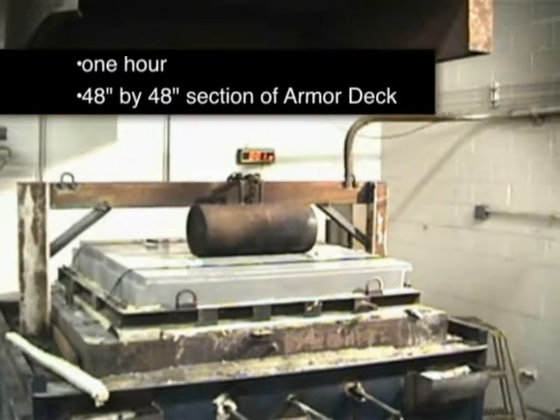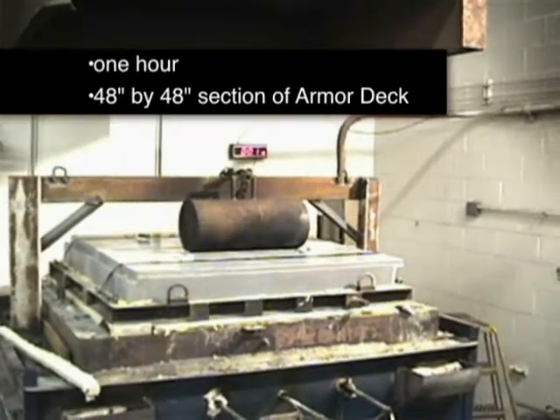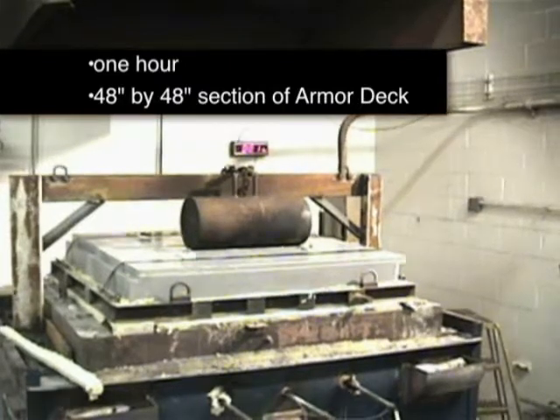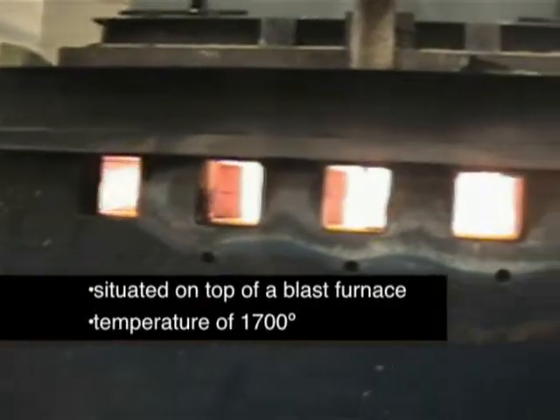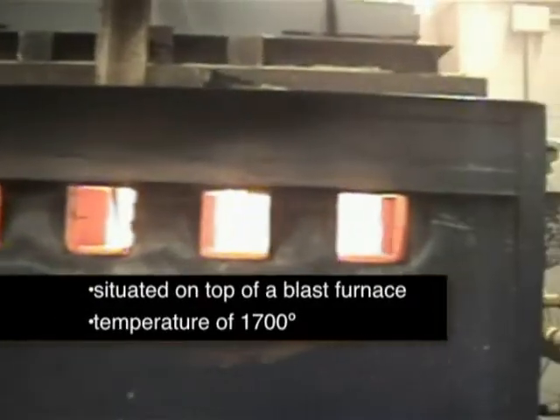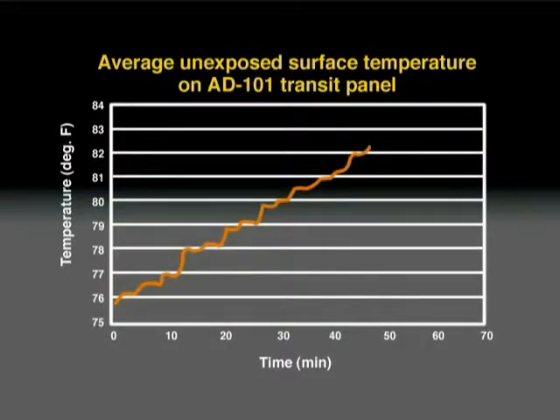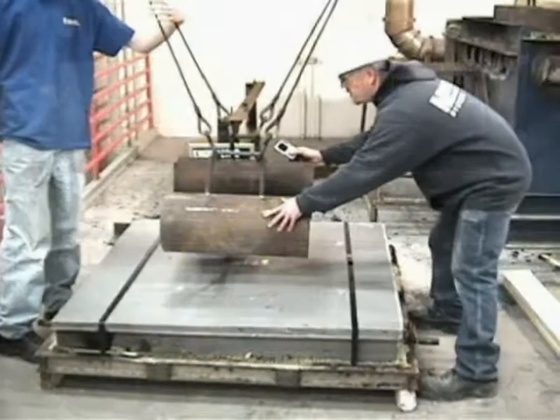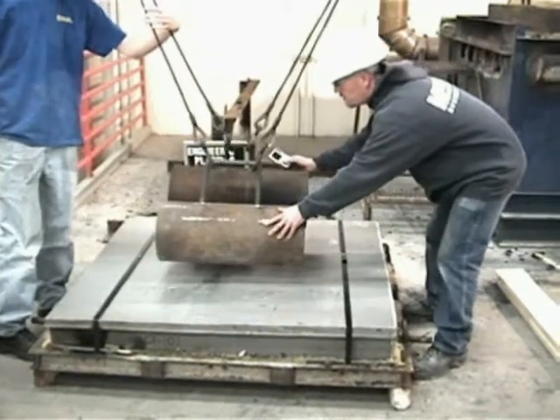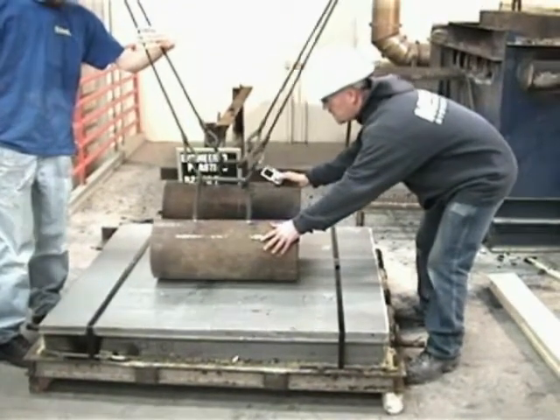The test ran for 1 hour and consisted of a 48-inch by 48-inch section of Armor Deck situated on top of a blast furnace with open flame, which maintained a temperature of 1700 degrees. Armor Deck maintained a zero flame penetration and produced only a 3% rise in top surface temperature of the allowable tolerance, while simultaneously withstanding a 500-pound static load. The Armor Deck panel was then removed from the furnace, and a 1,000-pound static load was applied with no deflection.